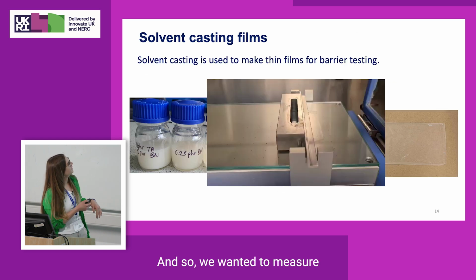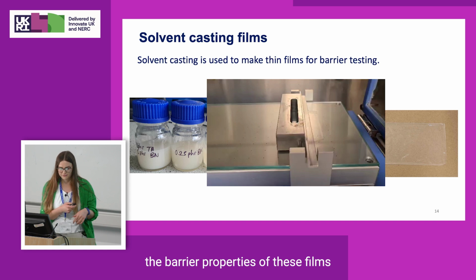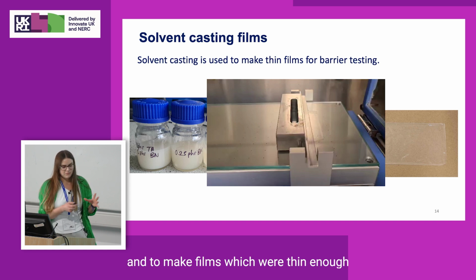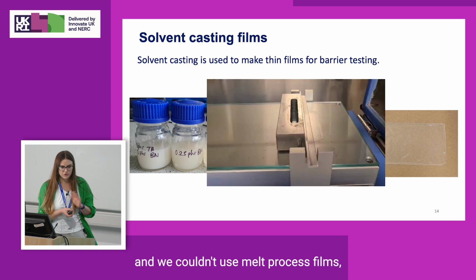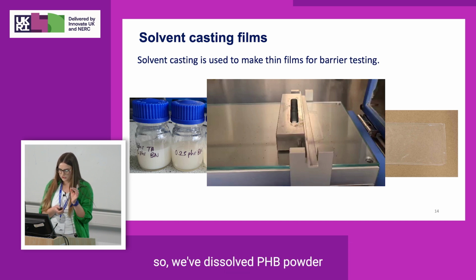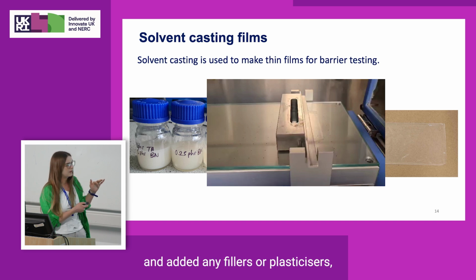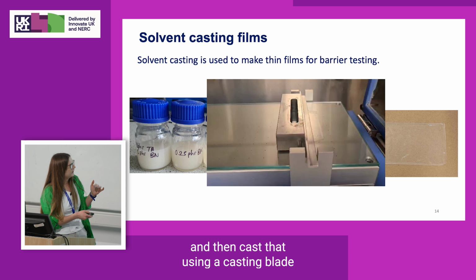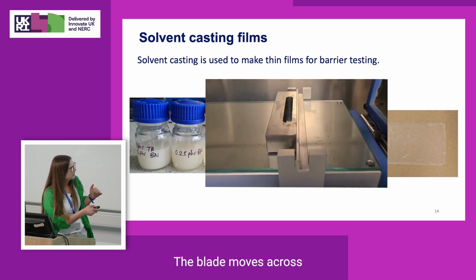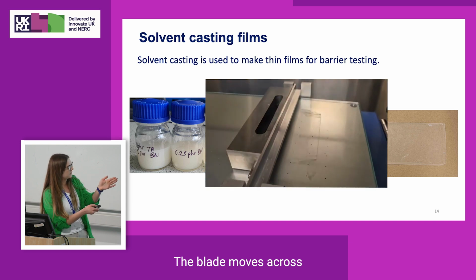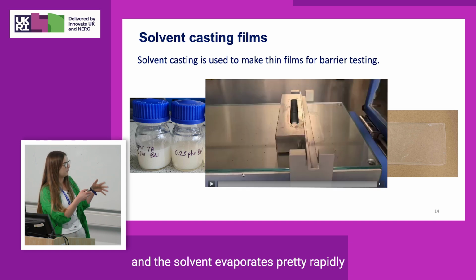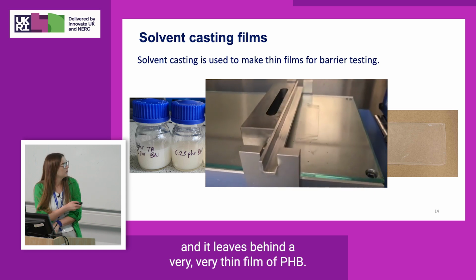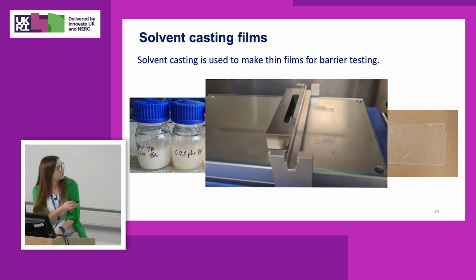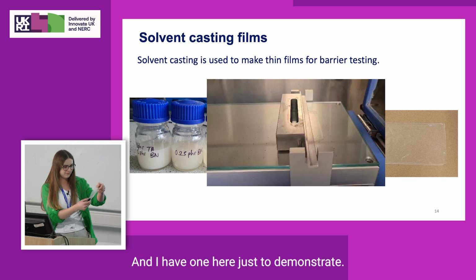And so we wanted to measure the barrier properties of these films, and to make films which were thin enough for barrier testing. We couldn't use melt processed films because they were too thick, so we've dissolved PHB powder and added any fillers or plasticizers, dissolved that in solvent, and then cast that using a casting blade onto a glass support. The blade moves across, and the solvent evaporates pretty rapidly, and it leaves behind a very, very thin film of PHB, and I have one here just to demonstrate.